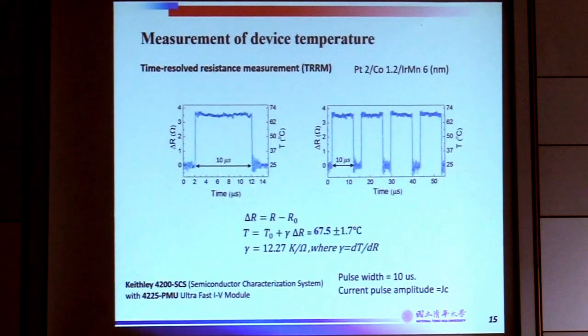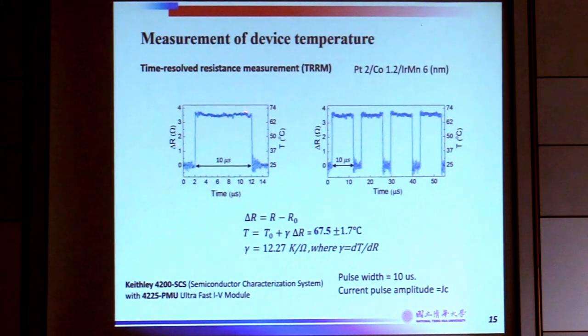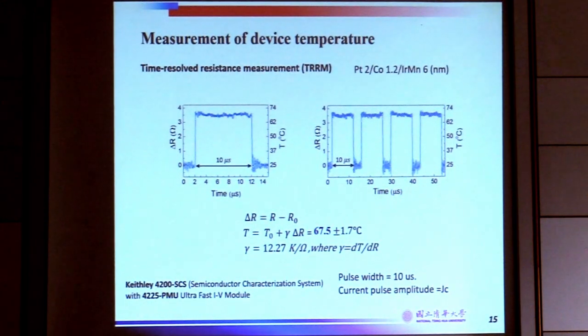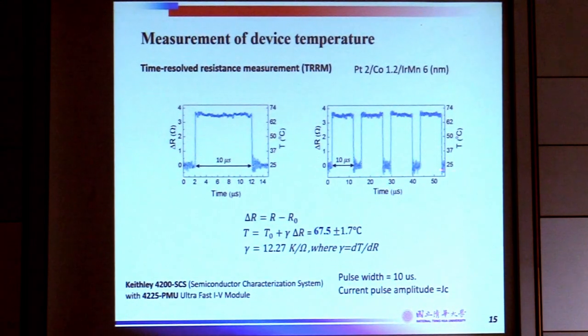Some people may argue there could be current overshooting, during which interfacial spins could be switched. So we developed an in-situ time-resolved resistance measurement using an ultra-fast IV module, which lets us monitor resistance during a short pulse — for example, a 10 microsecond pulse. In fact, we don't see any overshooting. Another concern is heat accumulation: after applying many pulses, one might see a gradual increase in background resistance. In fact, we don't see this either. Although there is a temperature rise, it is much lower than the temperature needed to switch the interfacial spins.